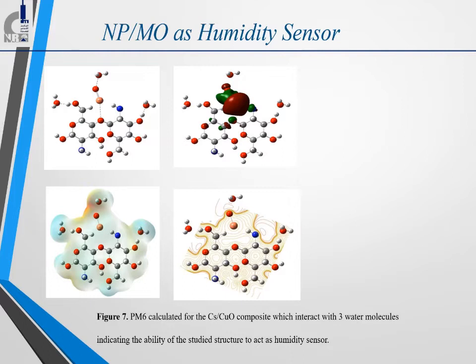And then we calculated the HOMO-LUMO band gap energy, total dipole moment, and molecular electrostatic potential to follow the change in electronic properties. Total dipole moment increased with a decrease in band gap. Also, the molecular electrostatic potential recorded a change in map colors, which confirmed that chitosan copper oxide could act as a humidity sensor.